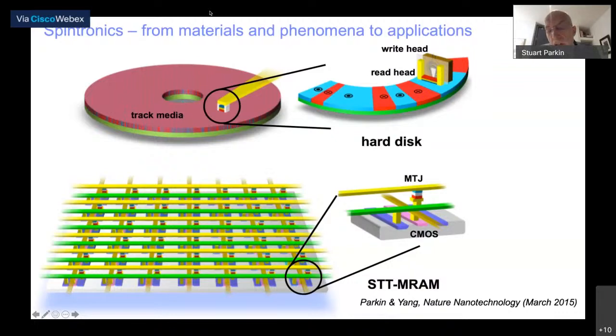We called it a spin valve, and a spin valve device is based on the physics of spin-dependent transport in magnetic metals and heterostructures, from which is derived giant magnetoresistance. The introduction of the spin valve sensing device, which is a metallic device but has a lot of complicated spin-engineered structure that I invented, was introduced by IBM in 1997 and enabled essentially a 10,000-fold increase in the storage capacity of magnetic disk drives.